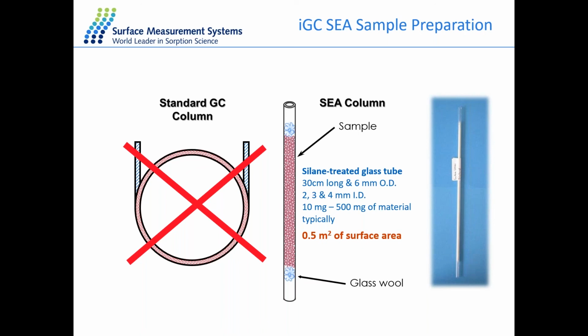Sure. So when preparing the column, once you prepare the column and you place it into the column position, before running your experiment, the system will run a constant flow of your carrier gas. And if you do see quite a large pressure drop, around 800 torr, then you'll have a message on your system telling you that you need to pack the sample more loosely. So in this case, there's a few ways to overcome this. We have different column sizes. We have 2, 3, 4, and a 10mm column. So you can increase the column size.